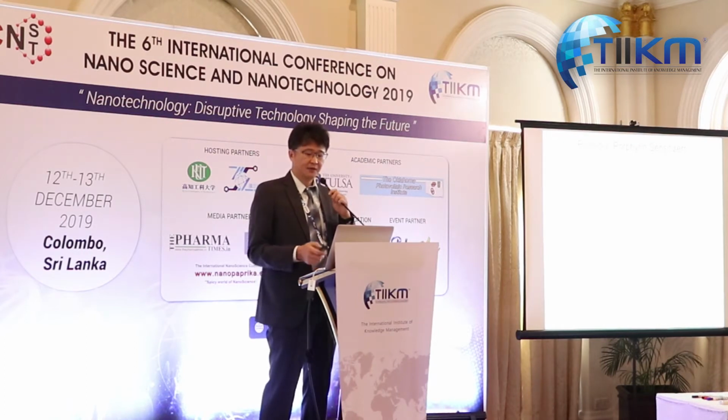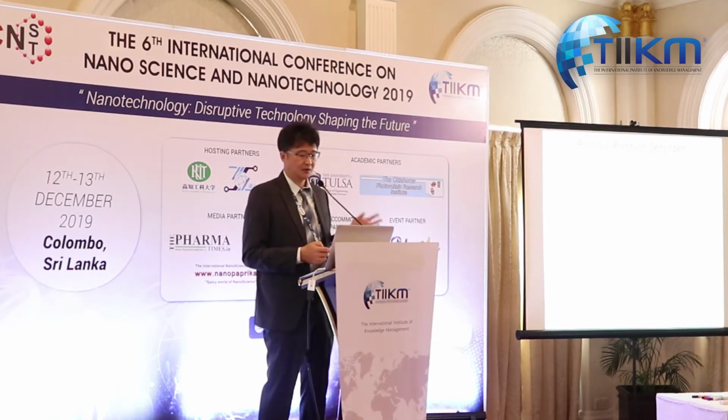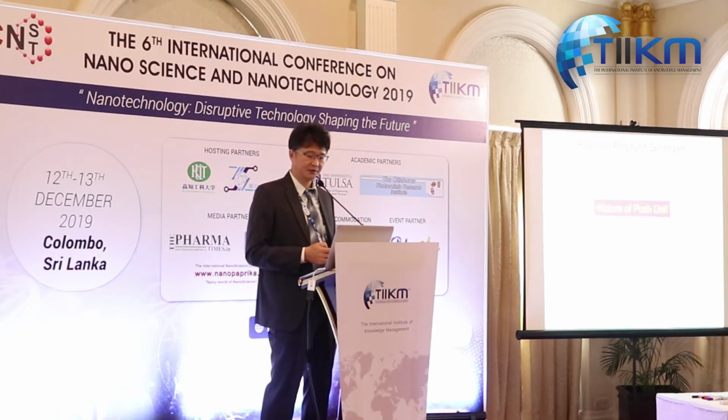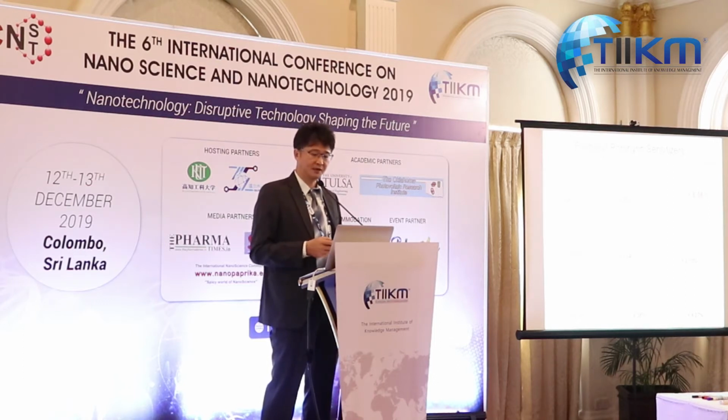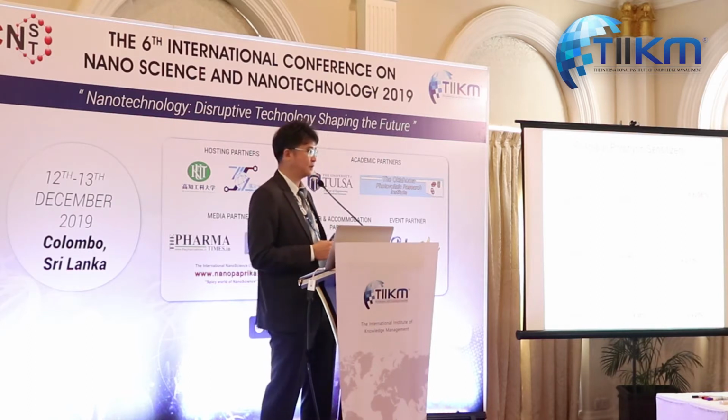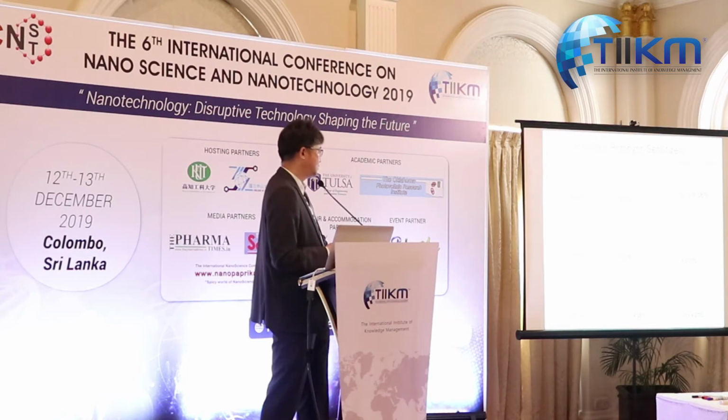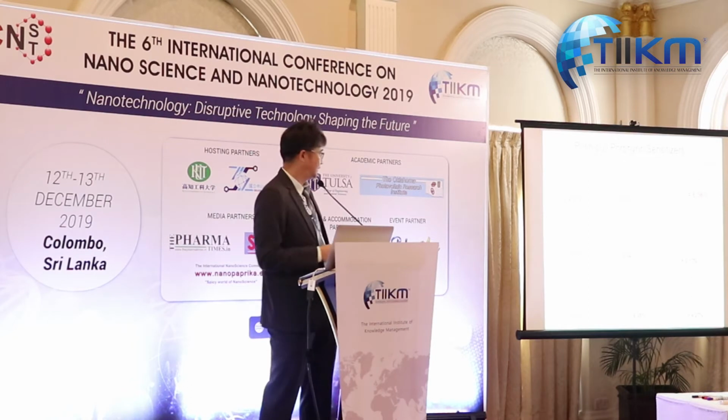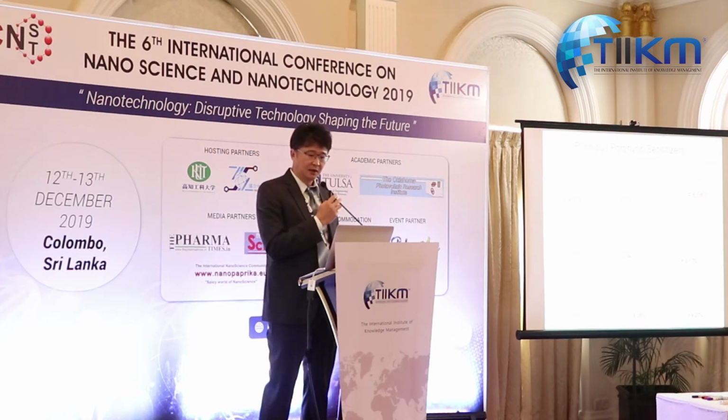So with these porphyrins, we were able to study how the nature of the push unit influences the cell performance. Among these porphyrins, YD1 to YD4 show higher power conversion efficiency than the reference YD0. And the triphenylamine substituted porphyrins show comparable efficiency with the reference. And then the efficiency of the triarylamine substituted porphyrin YD5 is poor.